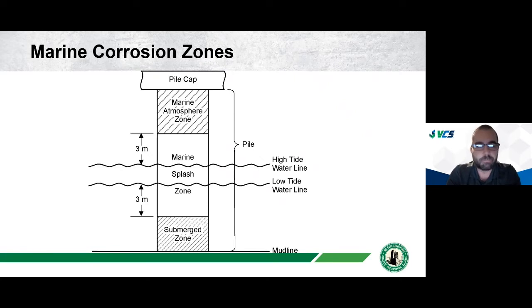You have the submerged zone, and I think commonly people get confused about the submerged zone. I often hear people say, oh, the submerged zone, there's no oxygen down there, there'll be no corrosion. That's not correct. Yes, there is less oxygen in the submerged zone. Being fully submerged constantly will slow your corrosion rate compared to the marine splash zone. But to say that there could be no corrosion down there is very incorrect and has led people to have some structures that have corroded in the submerged zone.